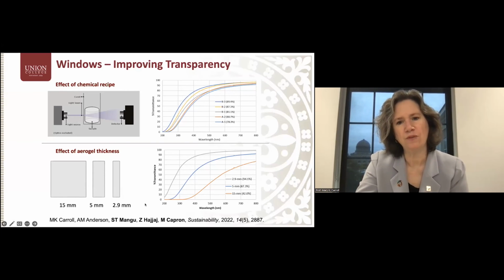And so if we go down to about 3 millimeter aerogels, what we can see is that these numbers over here are average percent transmittance from 380 to 720 nanometers, and we can get up to 94, 95% transmittance, which is comparable to optical glass in the visible region. And so by going to thinner aerogels, although we still have good insulating properties, we're able to increase transparency.